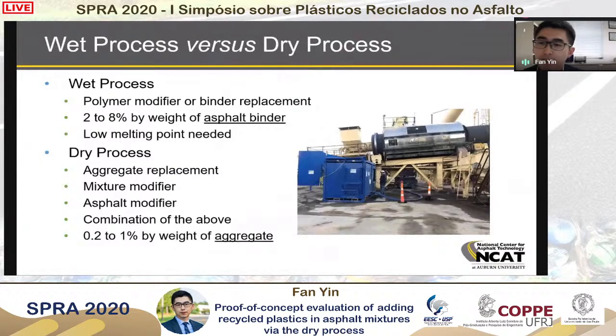I'd say we already have enough discussion about the difference between wet and dry process. Dr. Morris mentioned the wet process, where we're adding recycled plastic into the asphalt binder. In that case, the typical dosage is 2 to 8% based on the literature review that we did for NAPA and AI. And for the wet process, typically we would prefer recycled plastic with low melting point, because considering the production temperature of the asphalt mixture, those will be the plastic that can dissolve into the binder.